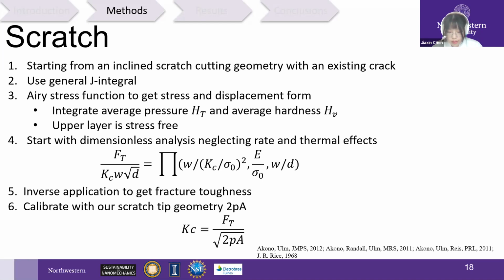The solution leads to the following equation connecting the horizontal force Ft to the fracture toughness Kc, which is Kc equals the horizontal force over the square root of 2pA. And 2pA is the probe shape function that depends on the geometry of the scratch probe as well as the depth of penetration d.